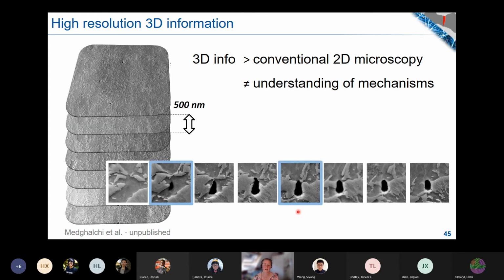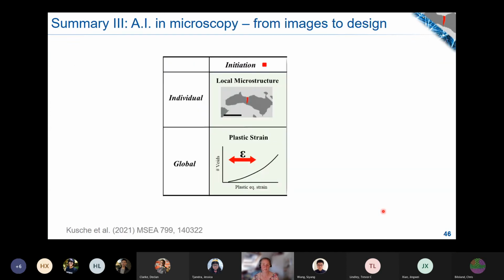For example, if you take this same damage site in different slices, so looking from the top to the bottom, then you go from something that looks like it happens at an interface to something that maybe underneath was actually nucleated based on the martensite crack. So that's something that we really want to dig into now, so that we can have a large area and fairly high resolution, at least in 2 dimensions, and combine this with 3-dimensional information.